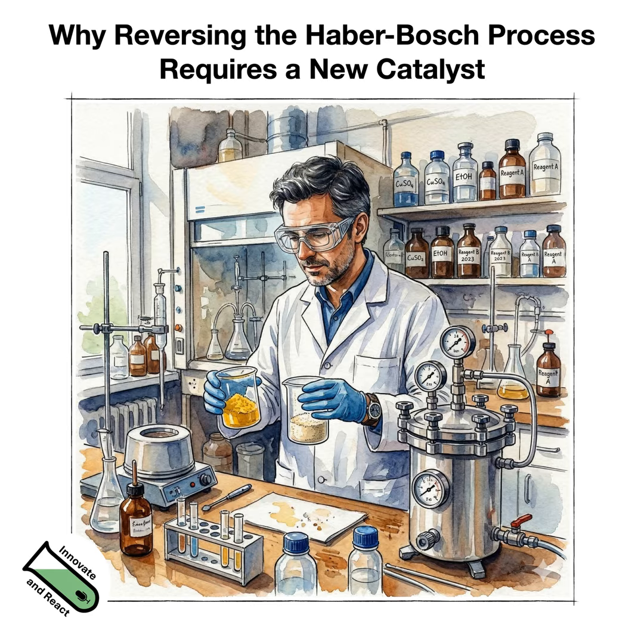And that is itself not necessarily porous. It can be a well crystalline material, not in all cases, but the porosity then develops when we, in subsequent steps, decompose those. So it's also multiple step synthesis. We co-precipitate the precursor. We first of all then typically calcine the precursor. So the precursor could be a hydroxide or a carbonate that you can calcine and decompose into the oxides. Then you have already an intimate mixture of the oxides. And that would be the stage where you also purchase catalysts. It's typically the calcined version.